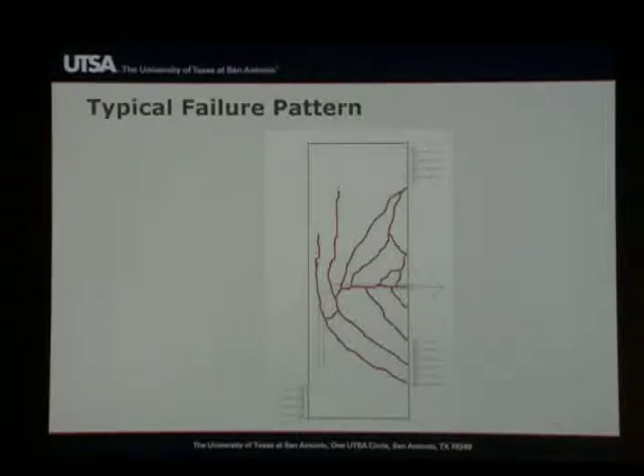If you're familiar with an anchorage test on an anchor, you end up pulling out a chunk of concrete. Well, that happened a lot in this experimental program. Test after test after test, you would see the hook bar come out with a much larger chunk of concrete than you would expect on an anchor. So, one of the intellectual exercises that we've done with this data set is, for example, look and see how these equations compare with the equations that we use for the design for anchors.